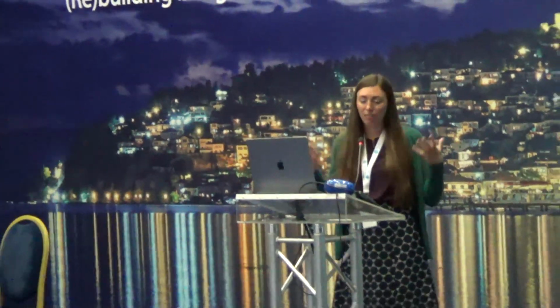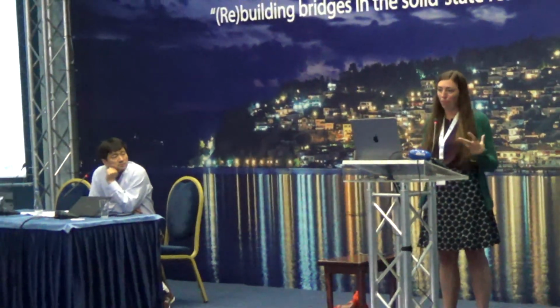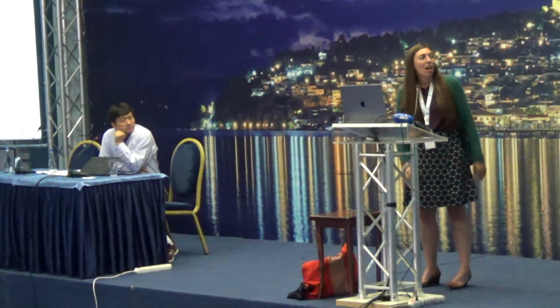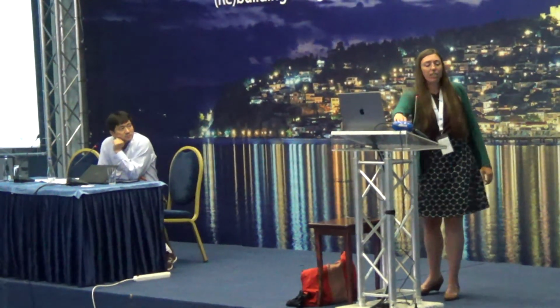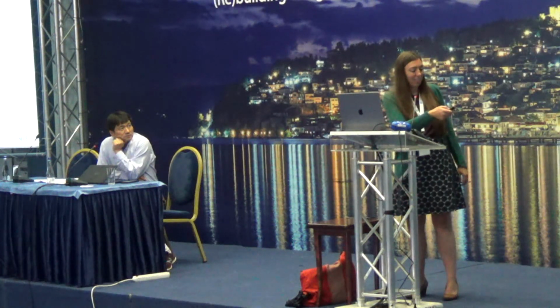Yes, so most of these materials are radiation sensitive, and so we minimize our exposure as much as possible. I'm collecting data for only about 30 seconds on the lowest setting the microscope can do, which helps, certainly. It does decrease the intensity values that I'm measuring to measure at such a low dose, but it's worth it for radiation-sensitive materials.